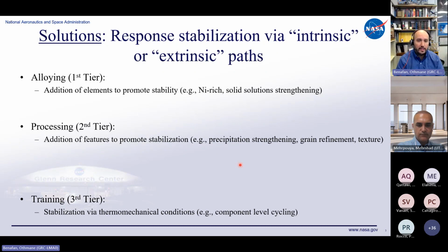And then once you have that chemistry locked in, you can go to the second tier, which is processing. This processing could be in the way of precipitation strengthening. For instance, if you have a nickel-rich alloy, you can age it to bring up precipitation to strengthen it. Or you can do some other way of promoting stabilization via grain refinement or texture or cold work or heat treatment, etc. All those are a second tier because you already have a locked-in composition. And it's a fairly common way of stabilizing the mechanical and thermal response in shape memory alloys.